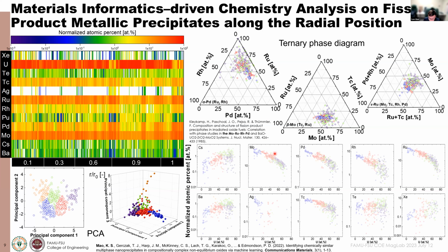This is only one tenth of the data, but you'll be able to plot a map of the composition of each and every precipitate. Then you can get a trend of the system and reinterpret this phase diagram with some classic thermodynamic model.